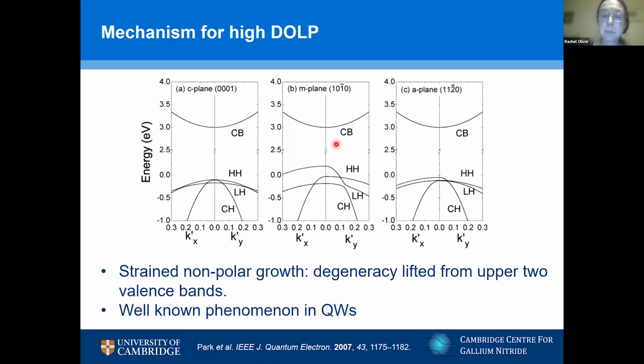However, for the non-polar planes, we have asymmetric strain, and that asymmetric strain lifts the degeneracy of the upper two hole bands. This is well known in quantum wells and gives polarized emission from quantum wells in these non-polar systems. And the same applies to the quantum dots. This lifting of the degeneracy results in the polarized emission that we see.